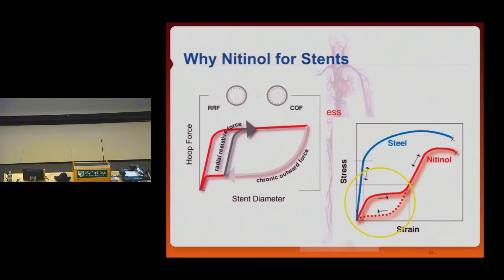So you have your fully expanded stent, say it's a 10 millimeter stent or something like that. You compress it into a 2 millimeter delivery system. So you compress the 10 millimeter stent into a 2 millimeter lumen of the catheter. You would follow this curve, the loading curve. Here's, say, 2 millimeters. You go into the body to the delivery site, you unload, you let the stent come out of the delivery system, and now it follows the unloading curve to the point where it hits the vessel wall.